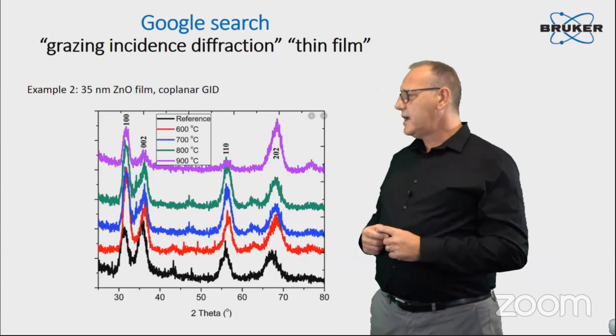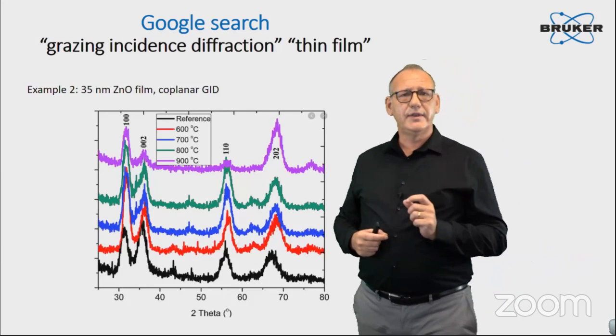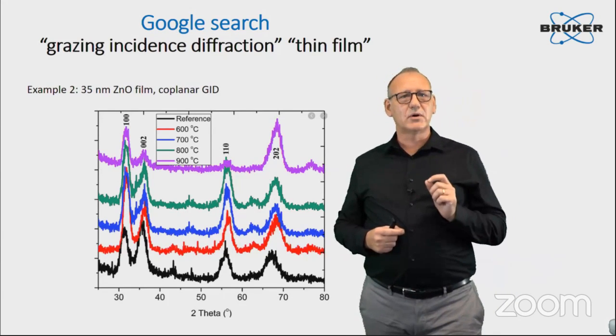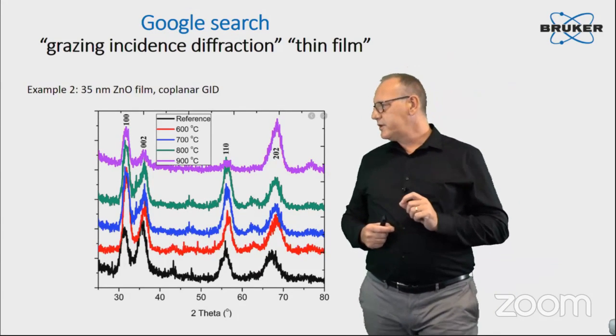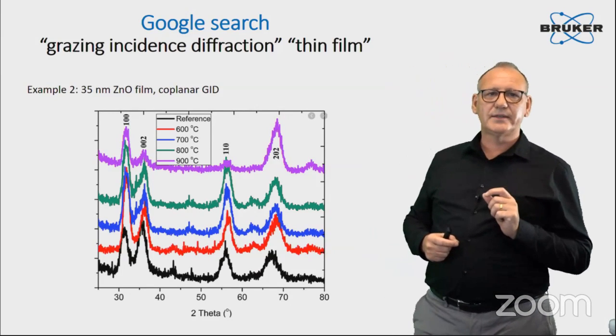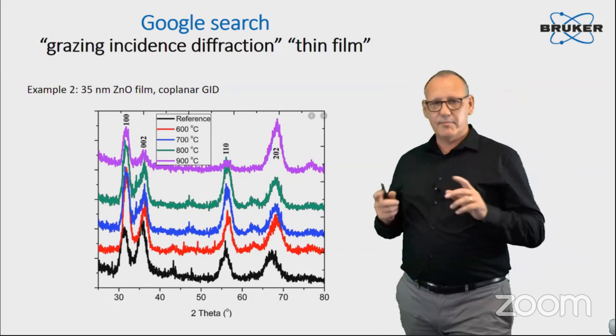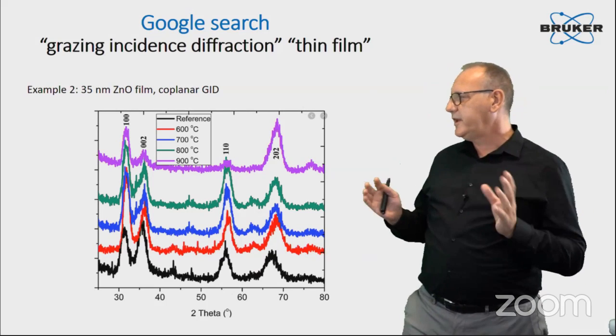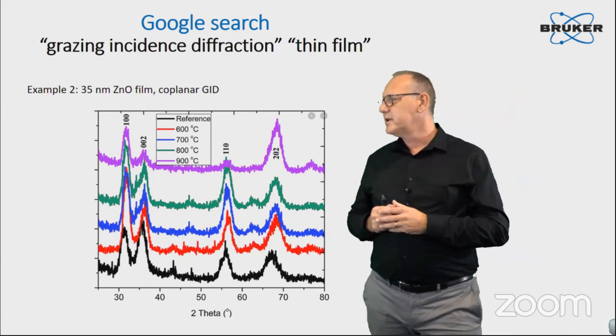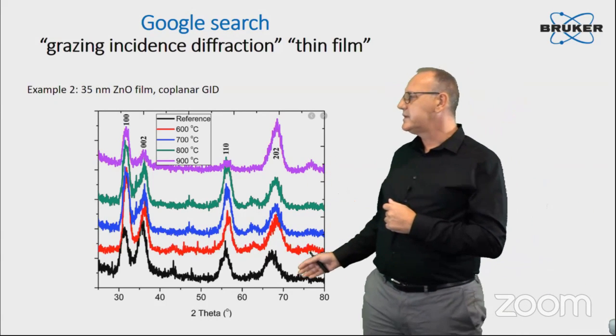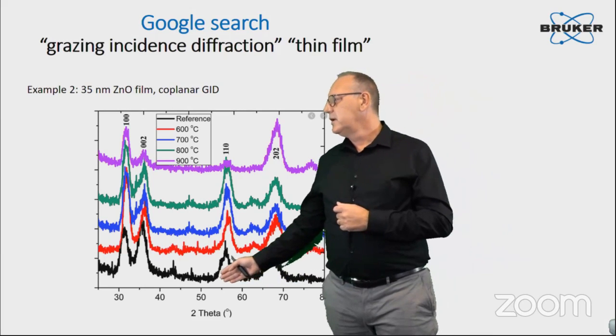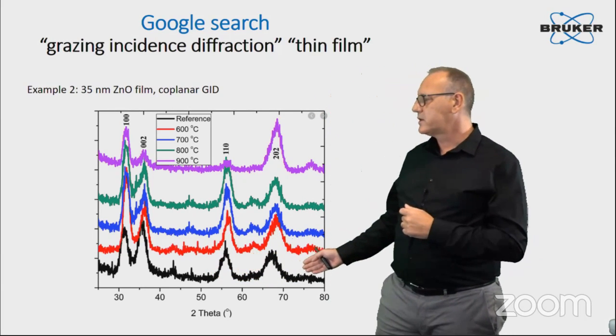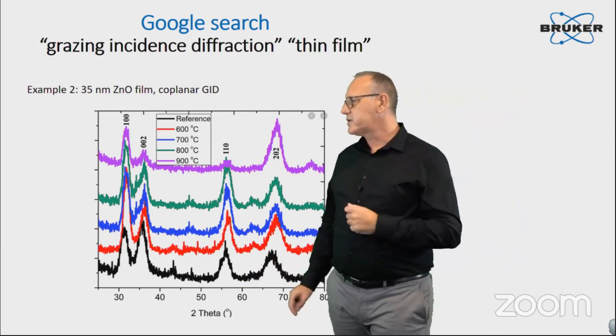This is another example of an even thinner layer. This is a 35 nanometer zinc oxide layer measurement in the so-called coplanar grazing incidence diffraction geometry. We'll come back to that later. We'll have some explanation about the different measurement geometries. But here, what we see is the initial material. This is 35 nanometer of zinc oxide, so a very tiny diffraction volume.